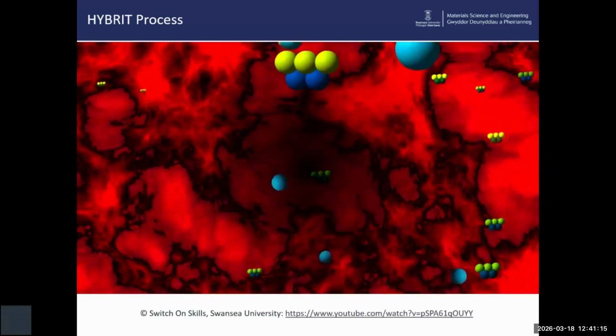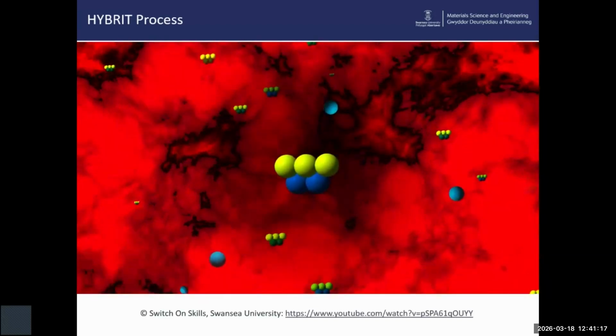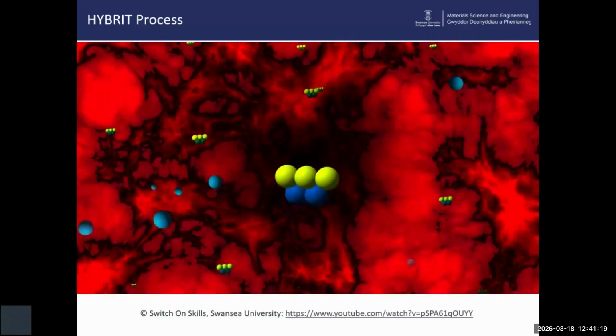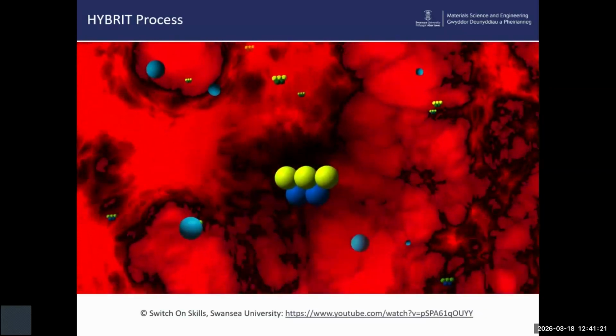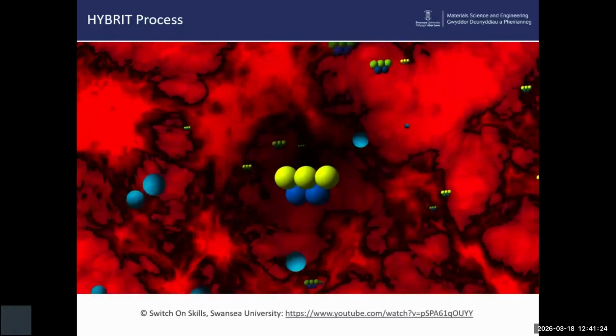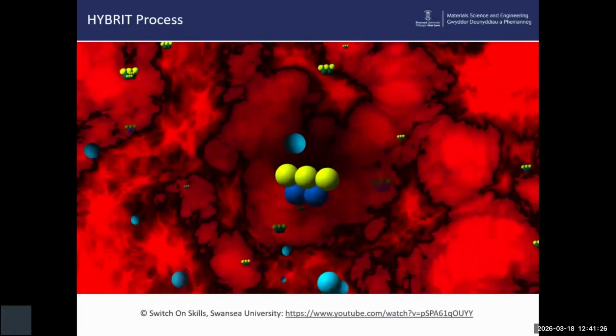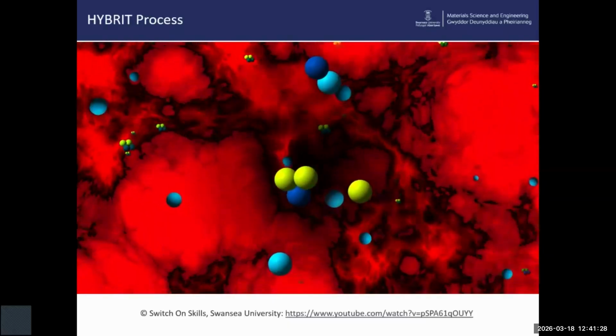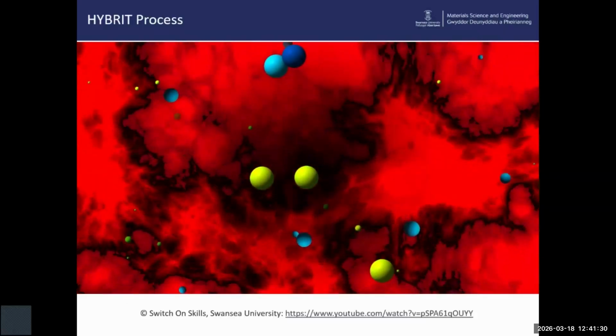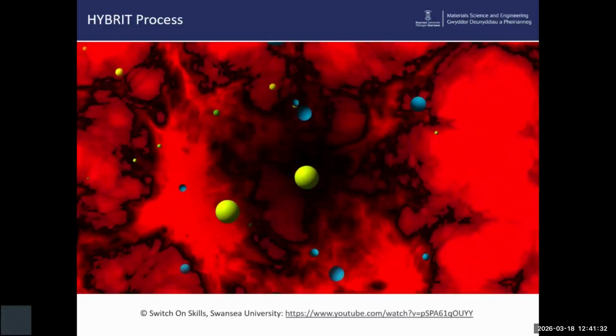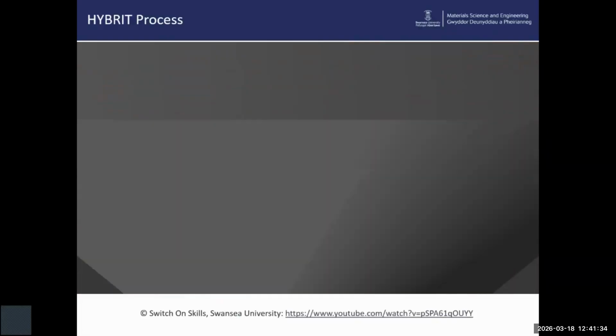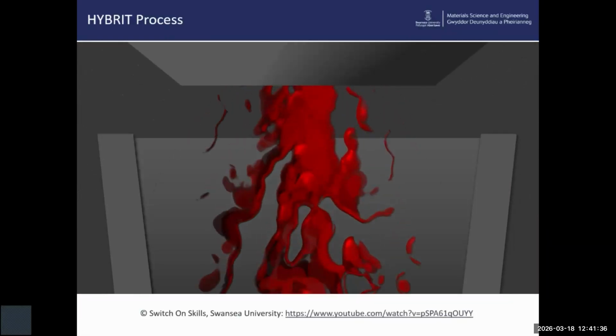Hydrogen rises to the top of the furnace as the iron ore descends. As the iron ore, in the form of hematite, Fe2O3, continues its descent down the furnace, it is gradually reduced by the hydrogen to magnetite, Fe3O4, to wustite, FeO, and eventually to metallic iron, Fe, which is collected at the bottom of the furnace.